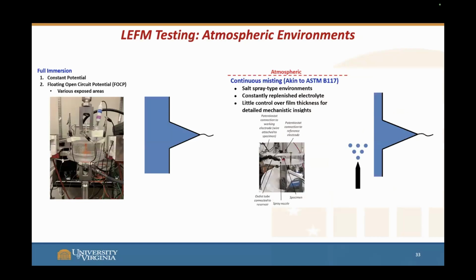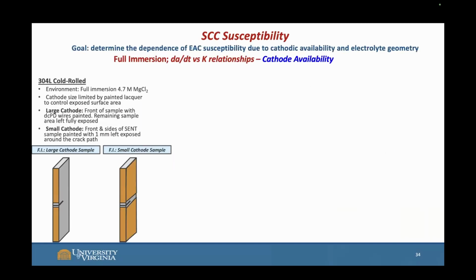It's the same thing that we talked about, but one of them was going to be full immersion, where we're continuously pumping full immersion solution through the cell, and the other one was a continuous misting spray. First, we did a full immersion cathode size availability test just to see what would happen if we limited the cathode size physically. We used a chromate lacquer to do this.